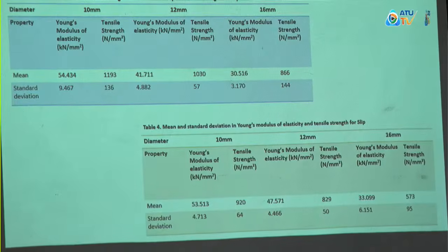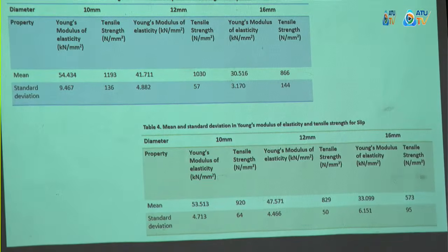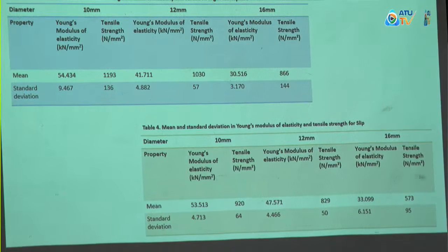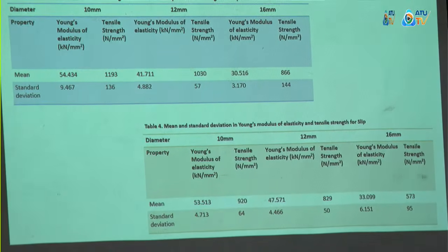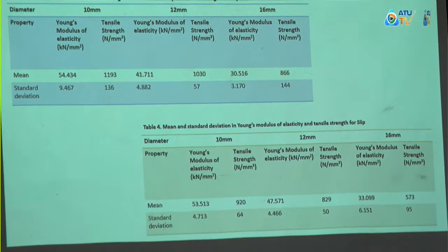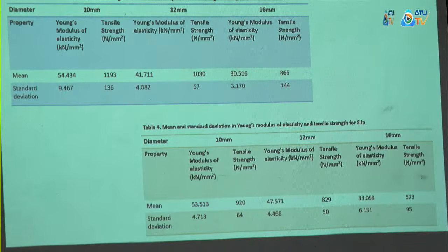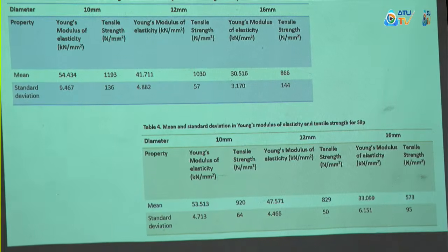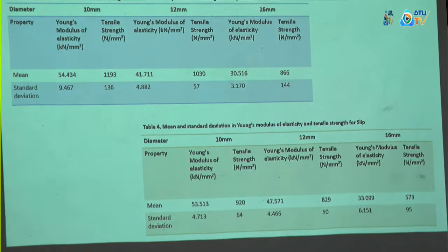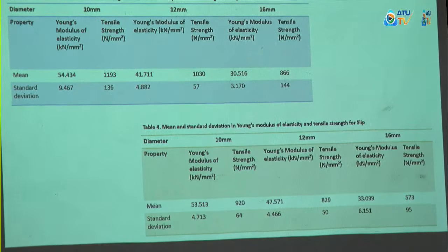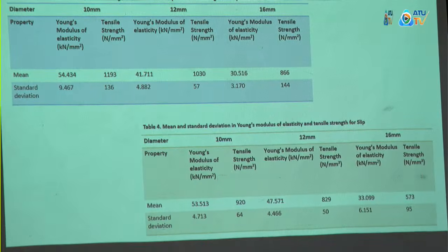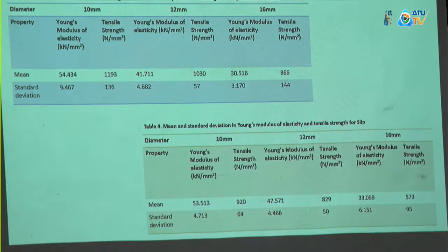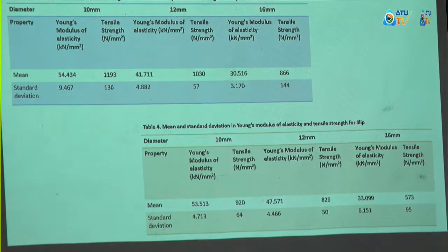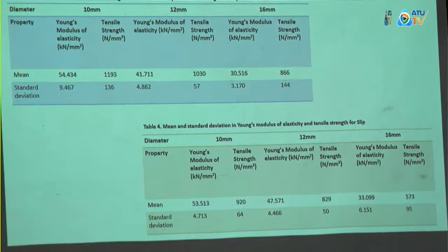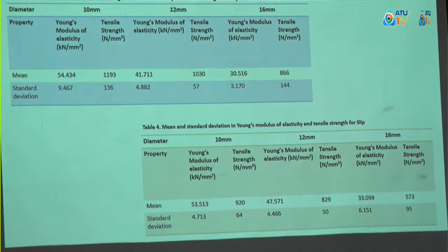Okay, this table gives us the results of the GFRP mechanical properties. For each diameter of bar, 10 mm, 12 mm, 16 mm, we have Young's modulus of elasticity and then the tensile strength. For the 10 mm you have 1,193 newtons per millimeter squared, for 12 mm you have 1,030 newtons per millimeter squared, and for 16 mm you have 866 newtons per millimeter squared, just to show that the smaller the diameter, the higher the tensile strength.